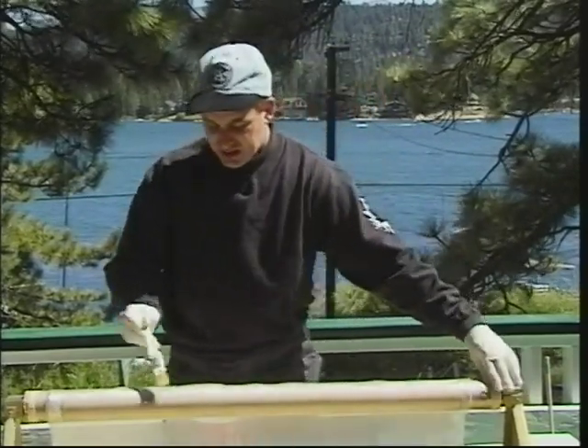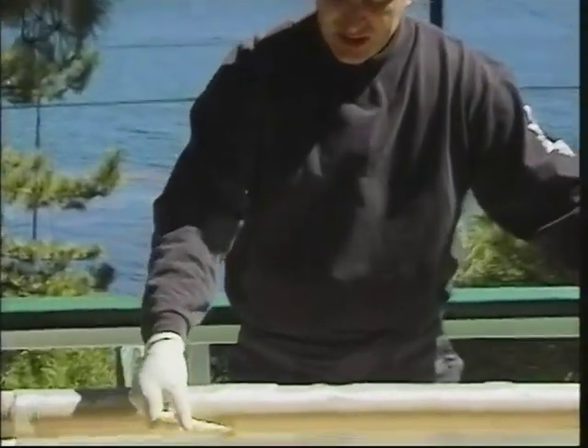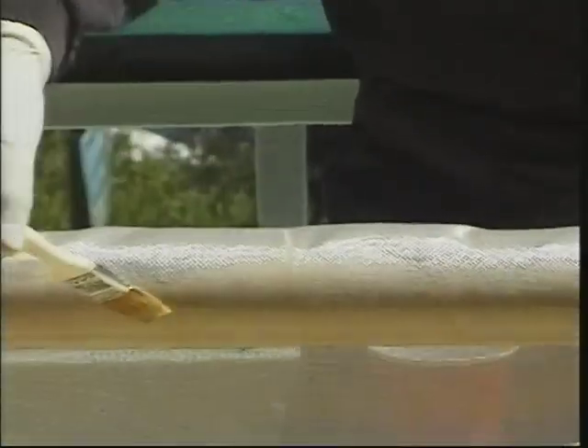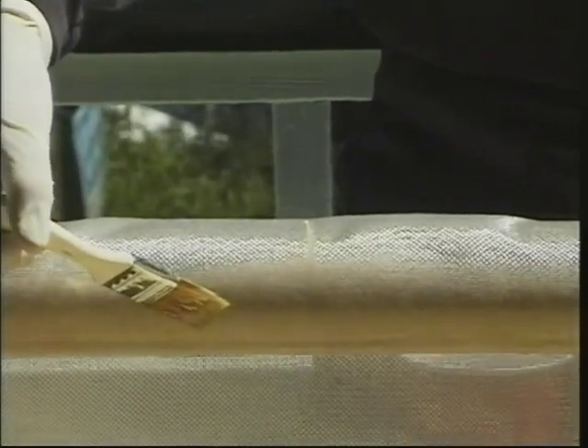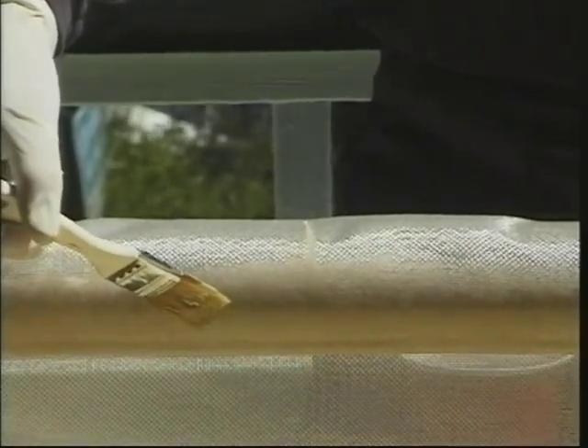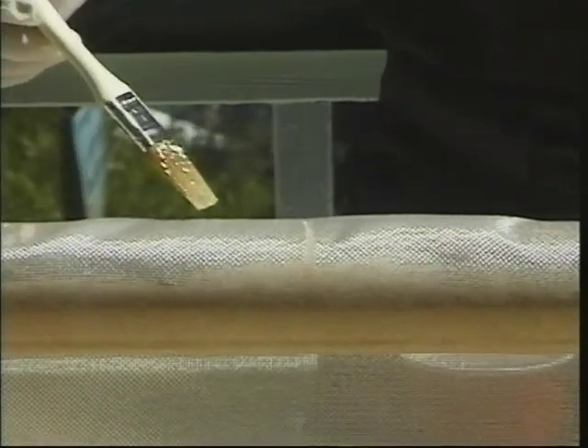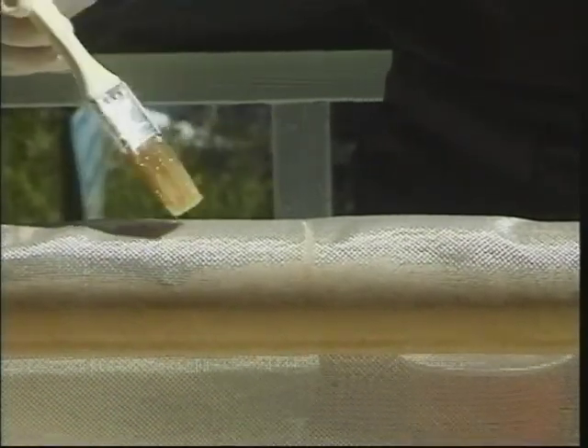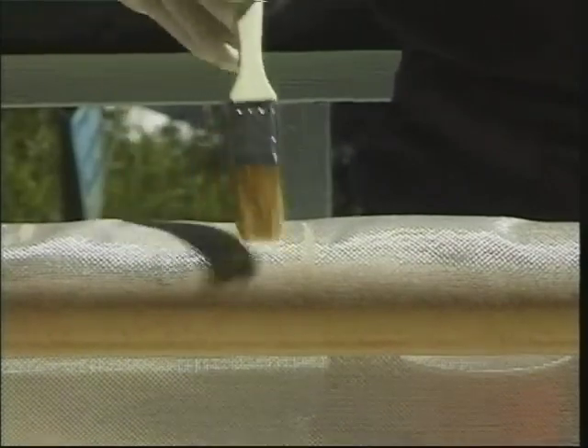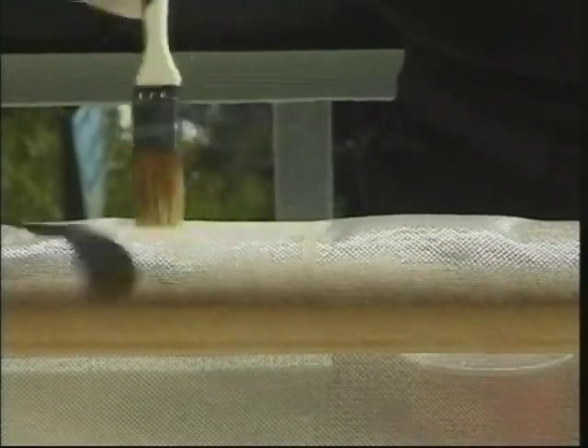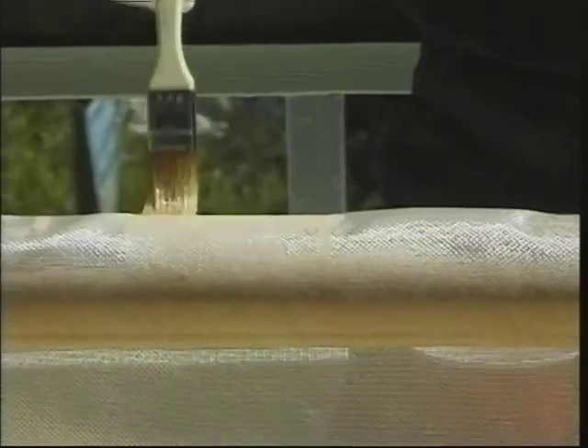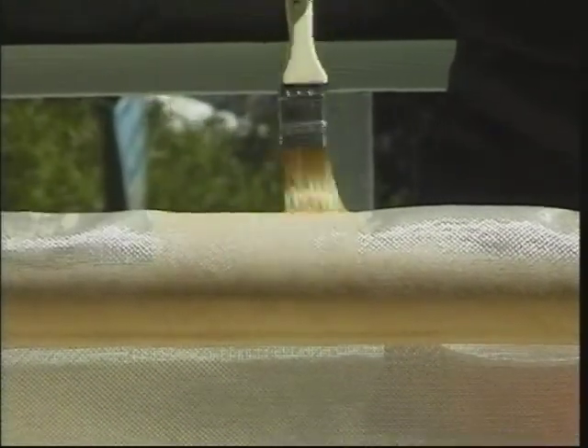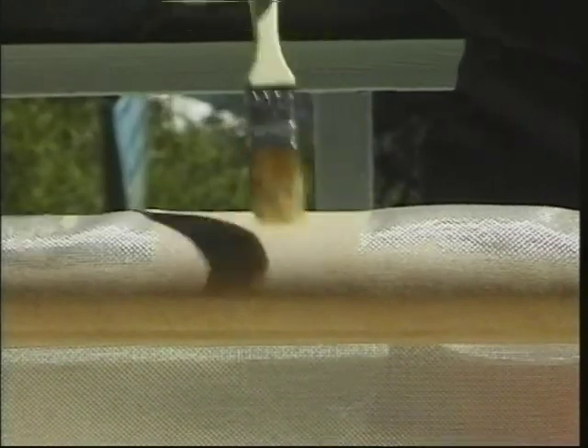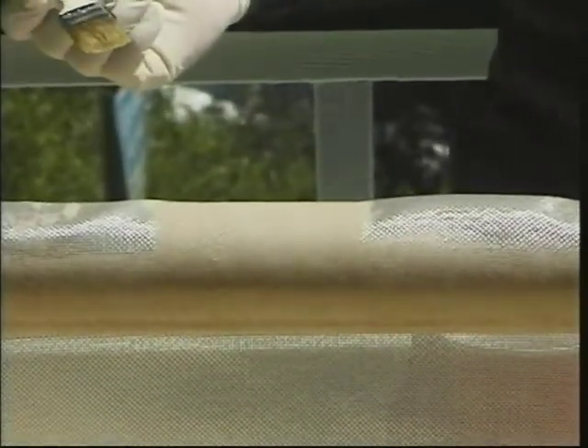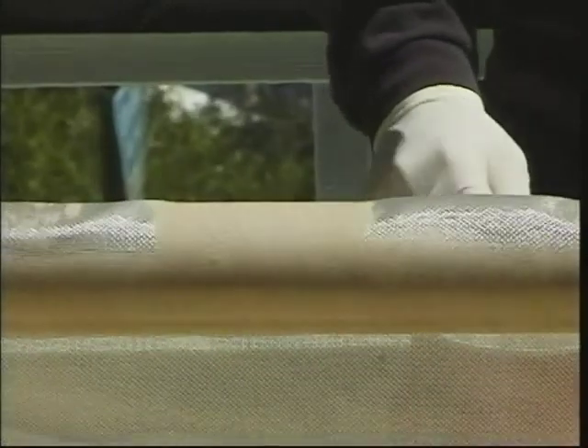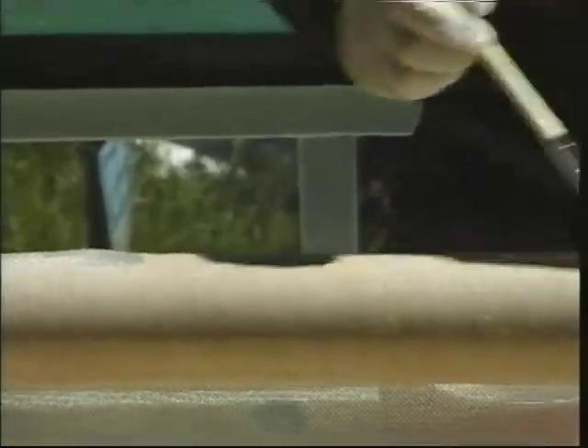Now if we could just zoom in on an area here. Down here is an area that I have glassed already, and you see the resin has saturated the cloth. It's clear in appearance, you can see right through it. Up here is cloth that hasn't been saturated yet. Obviously it's kind of glossy, metallic, pearly white. As I add the resin, you can see it saturates the cloth, and now you can see the tube underneath. So that's the appearance you're looking for as you work your way around.